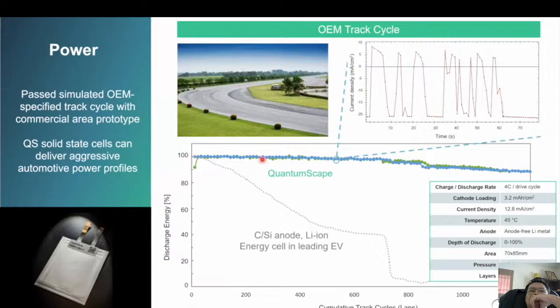And so this graph shows two of our cells and how they perform on that test, showing pretty gradual fade for over 1,200 laps around this track. This test is quite stringent. If you put a leading energy cell that came from a leading automotive maker on the same test, it fades much more quickly, just because this is a very aggressive test. And again, with all the test conditions listed here, this was done on the same generations of cells that I've been describing in the last few slides.